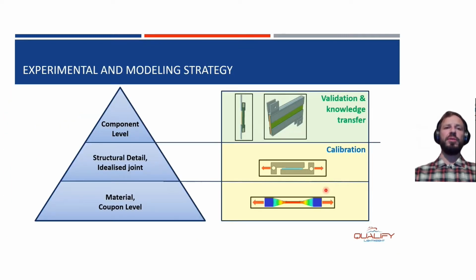How did we actually pursue the whole modeling approach? We started with a material level and a structural level. For that, we considered experiments, and we used those experiments to calibrate the material models and the constitutive models that are required for our high fidelity models you see on the top. We need to calibrate for the steel, for the adhesive. We need to look into the interfaces, composites, etc. And then in the end, we do the component level tests